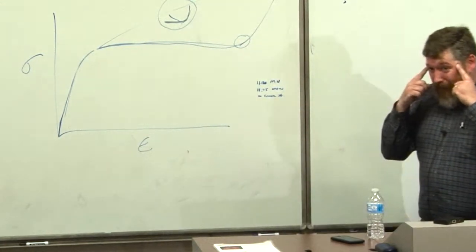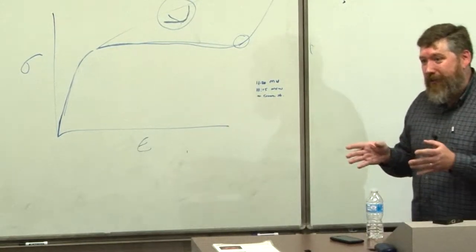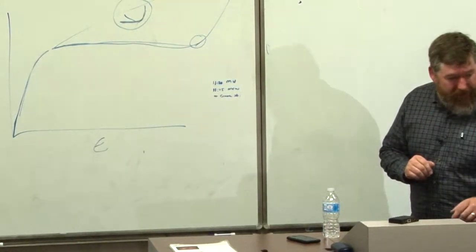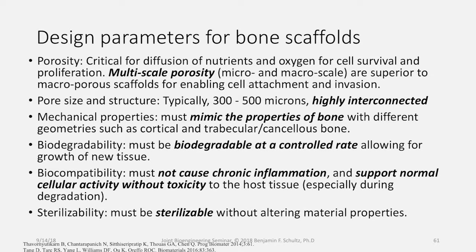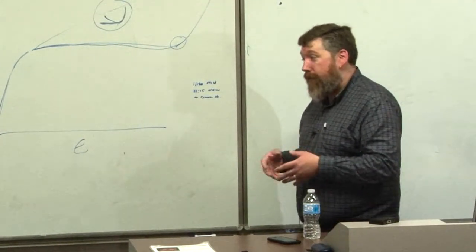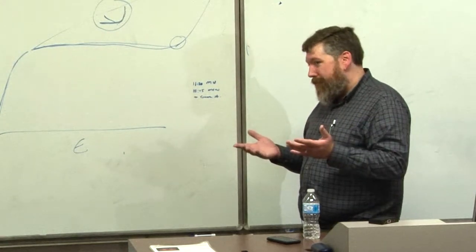These are some of the design parameters that we're trying to hit. We're trying to match porosity, the types of porosity, multi-scale porosity that might be in bone. We're trying to match pore sizes and structure, something that's highly interconnected. We're trying to mimic the properties of bone. We're also trying to control the rate at which these magnesium alloys degrade inside the body. So we're doing some alloy development with this as well. We also want this to be compatible, so we can't use anything that's toxic. And we also want this to be sterilizable, so that the sterilizing processes that are used don't destroy the material.